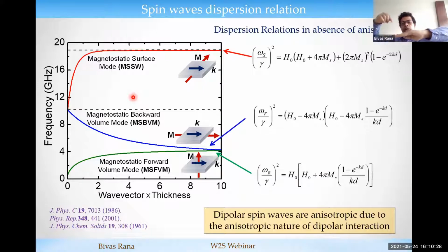So depending upon which surface you are detecting from, the spin wave amplitude for opposite directions of the magnetization you are applying could be different for this surface mode. But for the backward volume mode, the amplitude will be the same. So in that way, you can also identify. And of course, if you use Brillouin light scattering, then it's much easier because you can directly measure the frequency as a function of wave vector, and from the dispersion relation you can identify.